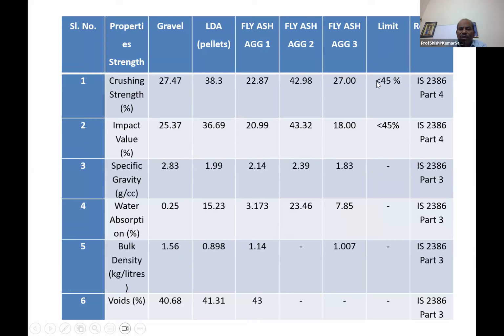Everything was satisfying, but actually which one is better? Crushing strength should be less than 45. Everything is satisfying, but less is better. So this is aggregate 1. This is impact value. This is specific gravity. Specific gravity wise, this is better because it is lightweight. 23, 27. Water absorption is less here. This is, I think, the best one. Water absorption is less here. And bulk density.